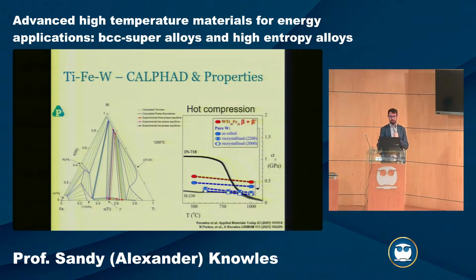So we can look at the flow stress, the yield strength versus temperature, benchmarking against a 718 nickel superalloy, and also some pure tungsten. And what we find is this tungsten superalloy, at 1,000 degrees C, is still maintaining half a gigapascal, so 500 megapascals, of strength, from a very, very simple alloy, from literally a 6-month to 1-year project, and we can already beat nickel-based superalloys and tungsten. So this gives us confidence to continue going down this path.